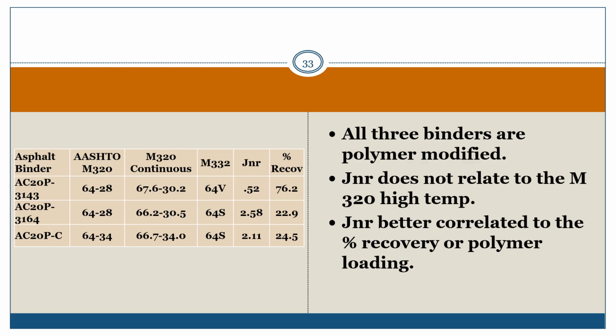Here we're trying to show you how there can be some very, very big differences, both in the J&R value and in the percent recovery. In this particular case, if we look at the M320 continuous grade for the 3 binders, they're all very, very similar, all within about a degree, except this one is -34. So you get 2 -30s and a -34, but you get a 66.7, 66.2, 67.6. But when we go to the J&R values, we see that there is a big difference.